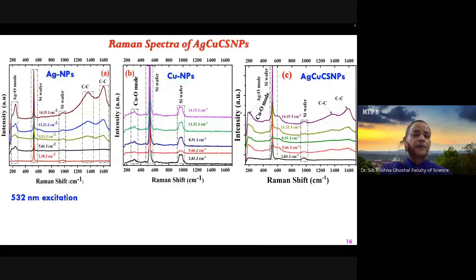When you look at the Raman spectra, as I say, Raman measurement is the most important measurement for these applications. If we look at the Raman spectra of this nanoparticle, we see that silver oxide modes are there, because the material is in water, so oxidation will happen. Silver oxide is a semiconductor with a good optical band gap, and a very good antifungal and antibacterial agent. So this is a pure silver oxide mode. We also have water molecules around these nanoparticles.